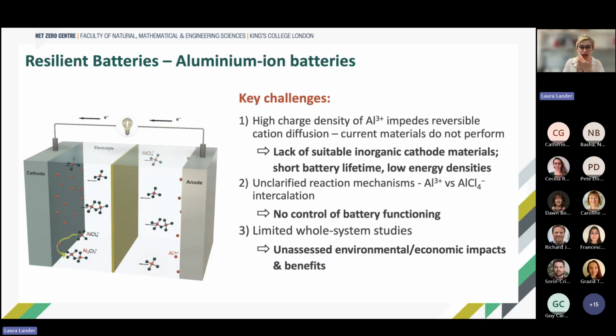And this leads to the fact that we can't really extract and intercalate our aluminium because it gets stuck within the material. This often leads either to short battery lifetimes, because our material, for example, just decomposes when we put too much pressure and try to extract our aluminium, or we can't really achieve the theoretical energy densities because we can't really intercalate aluminium. So there are a lot of different difficulties replacing lithium with aluminium in terms of cycling performance.